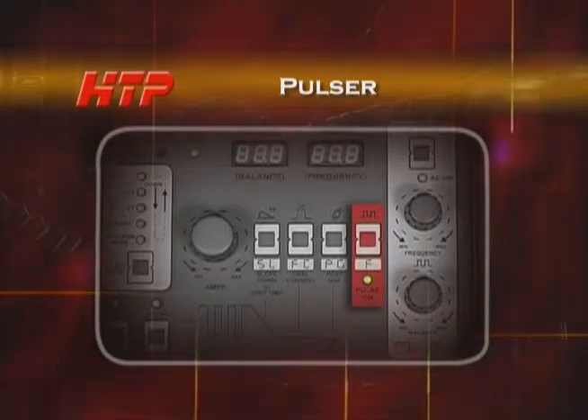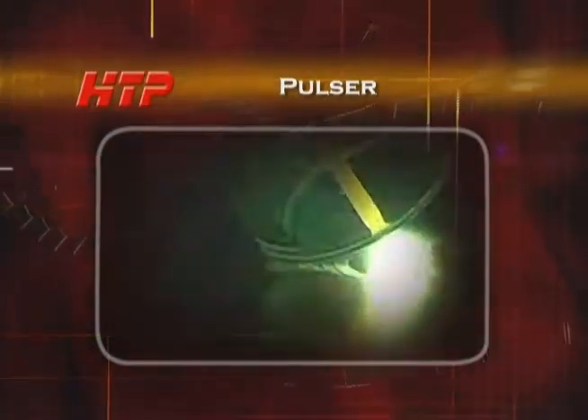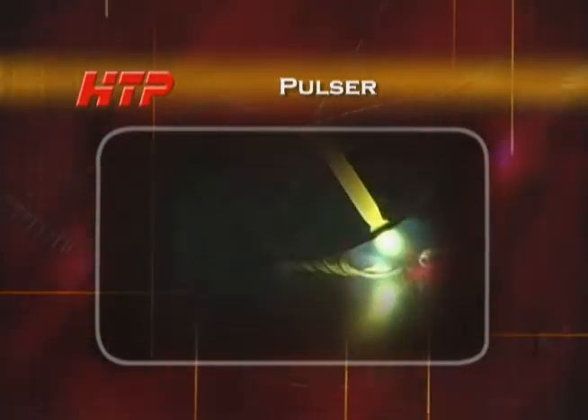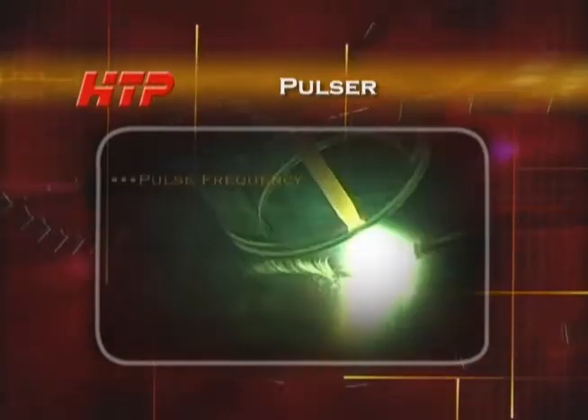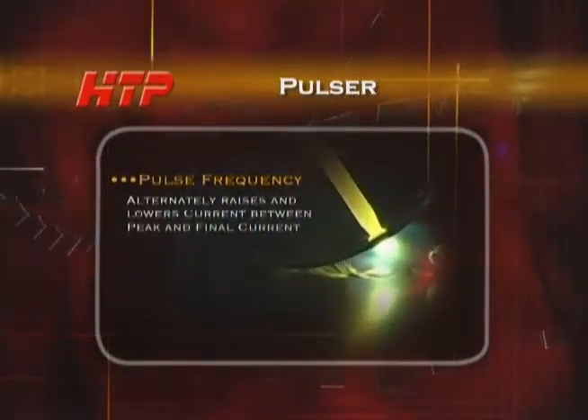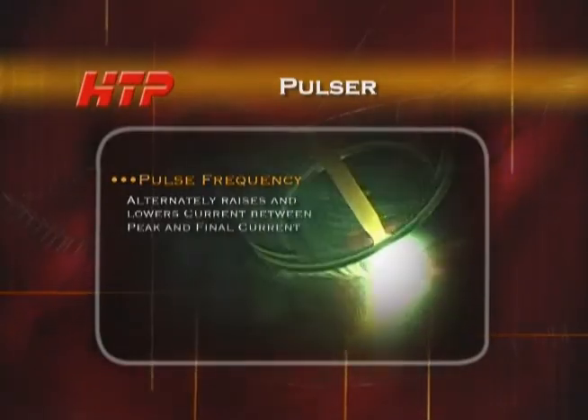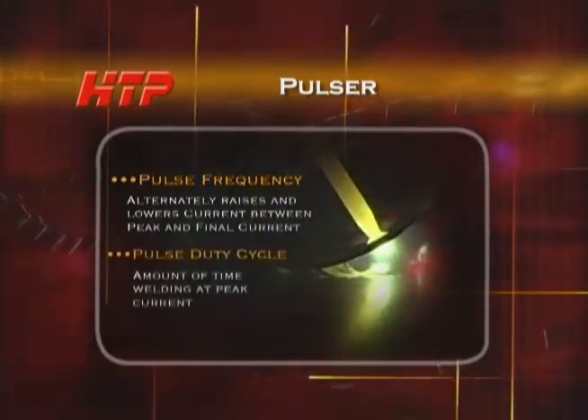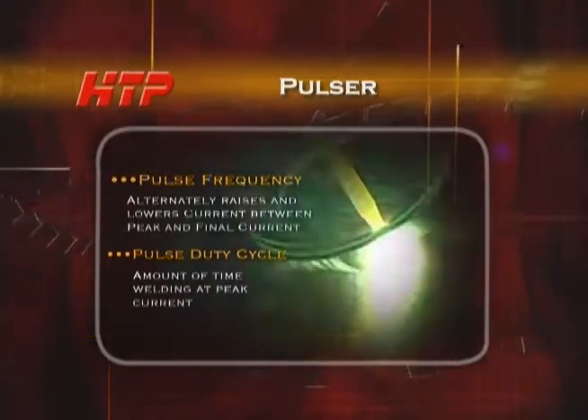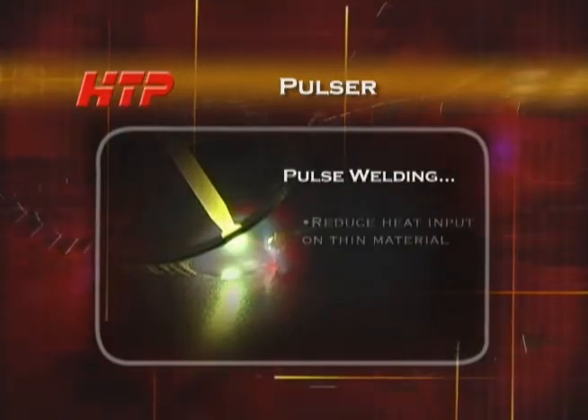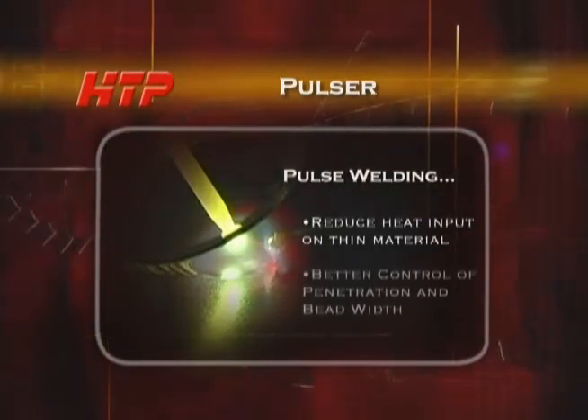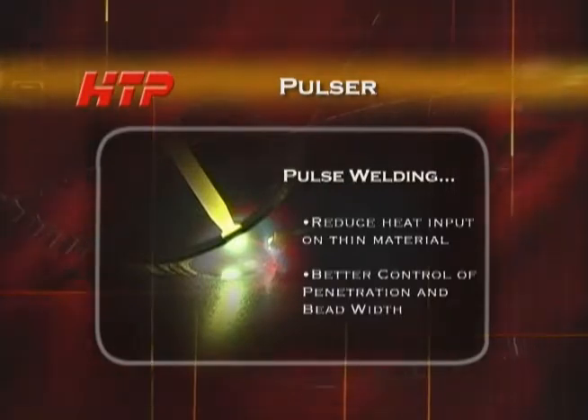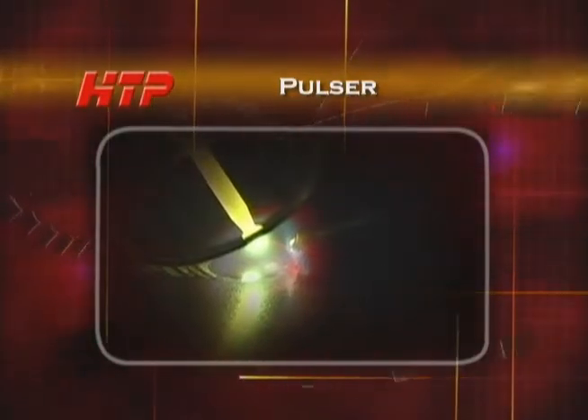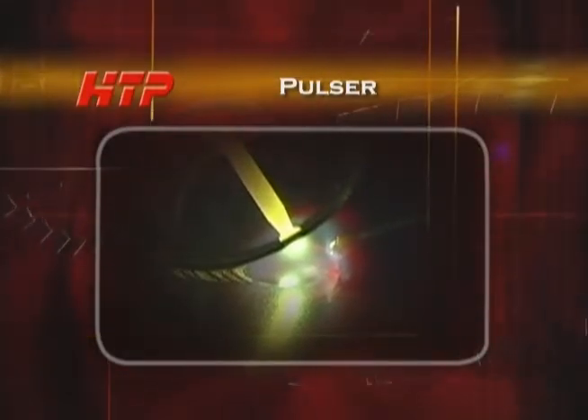The pulser alternately raises and lowers the welding current between the peak current and the final or background current. This is done a certain number of times per second, which is the pulse frequency. Furthermore, you can vary the amount of time you will be welding at peak current, which is the pulse duty cycle. Pulsing can reduce heat input on thin materials and give you better control of penetration and bead width. Using low pulse frequency can sometimes make it easier for the novice welder to time the addition of filler metal